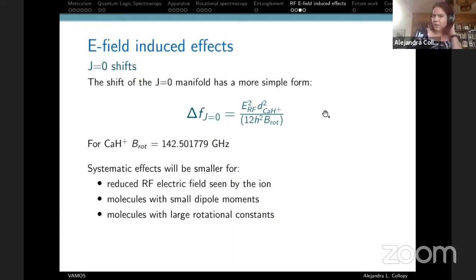This can be a little bit complicated to write down, but the shift of the J equals 0 manifold in particular has a fairly simple form, which we can write down as: the frequency shift is proportional to the RF electric field squared times the dipole moment of the molecule squared over the rotational constant. As I've shown you earlier, we spent a lot of time measuring the rotational constant pretty carefully. So if we were to do some frequency measurements and vary the RF electric field, we can get some information on the dipole moment of the molecule.